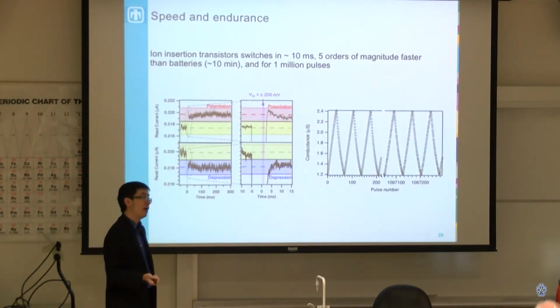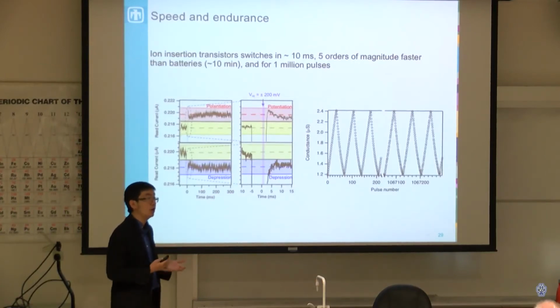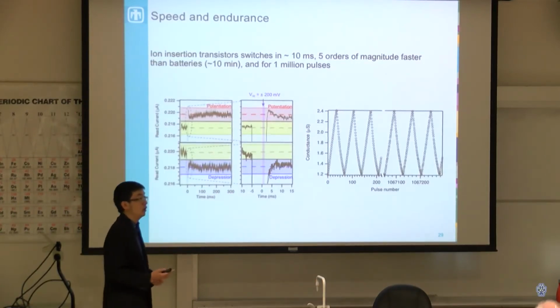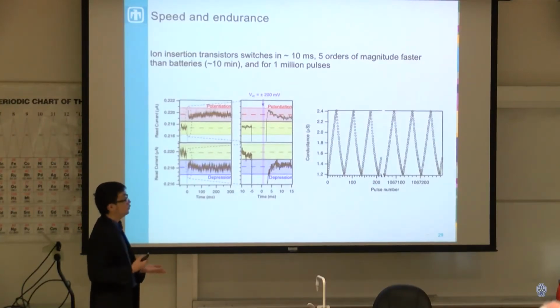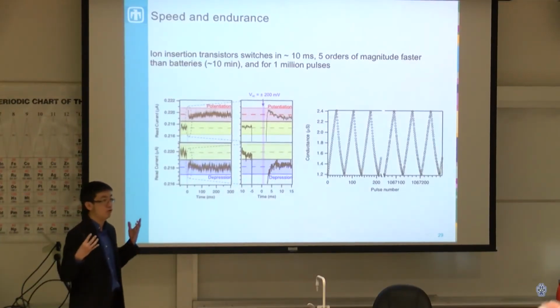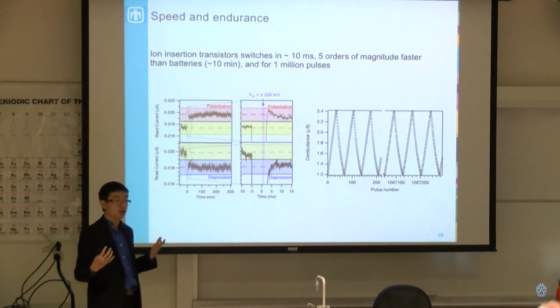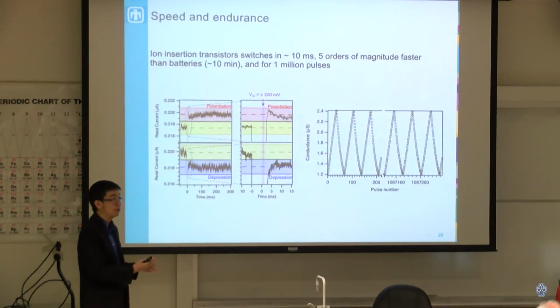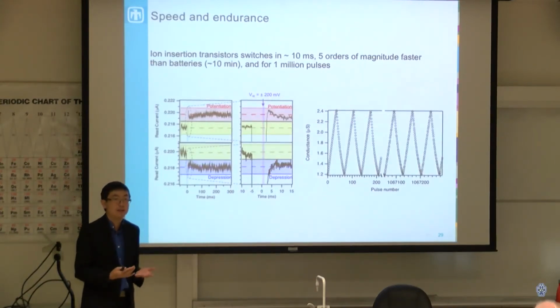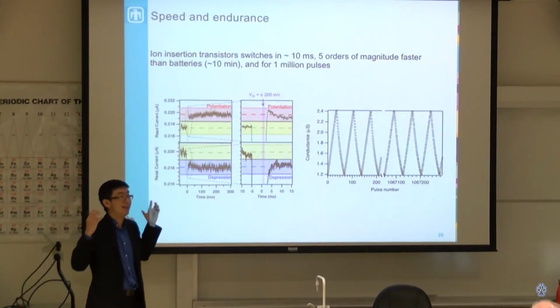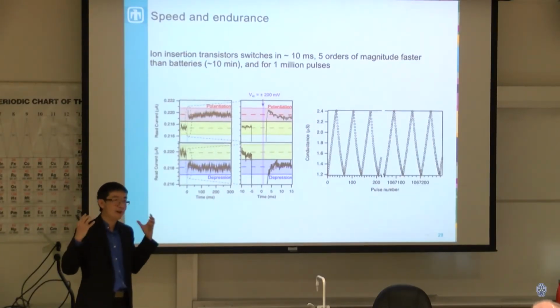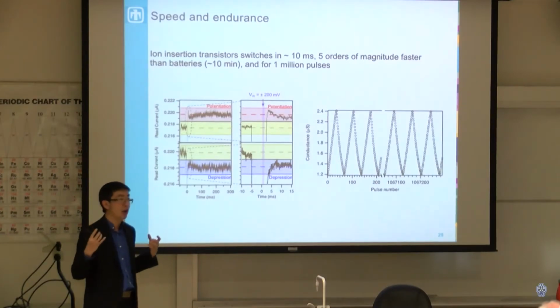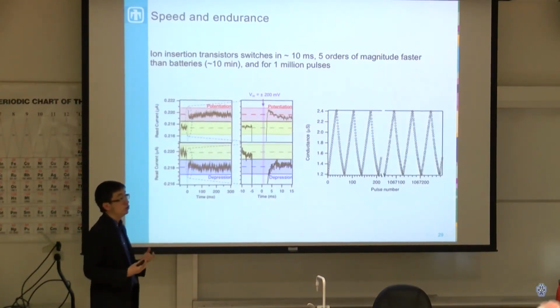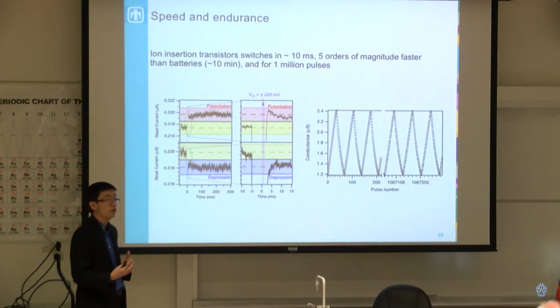However, if we think about non-volatile memories, the switching speed is already on the order of microseconds. So we are pretty close to that already. And the advantage is when we do neuromorphic computing, the benchmarks for how fast we do things are not nearly as strict as more high performance computing. So for instance, if we think about autonomous cars, our cars really only need to operate about as fast as we do. We don't need cars that can work faster than we can. And our brains operate only on the order of about 10 hertz or so. So when we have switching speeds in the kilohertz, we can conceivably achieve similar types of behavior as the cars for many of these applications.